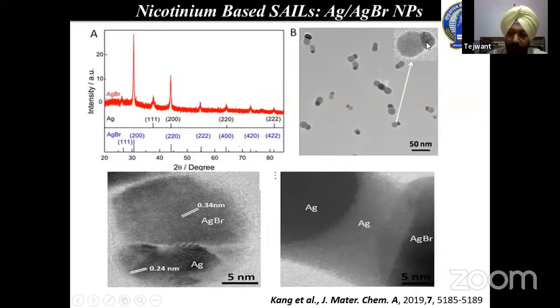Both the areas giving the different contrast have been further examined by high resolution transmission electron microscopy, where you can see the lattice planes, and the distance between the adjacent lattice planes is very specific for the specific material. It is 0.34 nanometer for silver bromide and 0.24 nanometer for silver. So from this lattice structure we could come to know that the area showing the lighter contrast is silver bromide, and the silver, which is in the darker contrast, is growing from the silver bromide. That has also been established from transmission electron microscope images done at some other places.